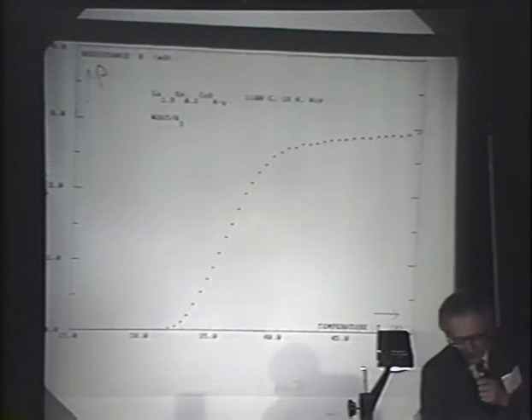We have a rather sharp susceptibility transition and a nice plateau at low temperatures, indicating a rather large Meissner effect, I think of order 40 or 50% of the sample. This is then further verified if we go over to resistivity data, which show similar sharp transitions, the resistivity going to 0 at approximately 32 degrees Kelvin. A step further, at this time in the beginning, I believe, of February, was to take this rather nice sample and to begin to look at magnetization loops, in particular below the transition temperature, and to work our way down.